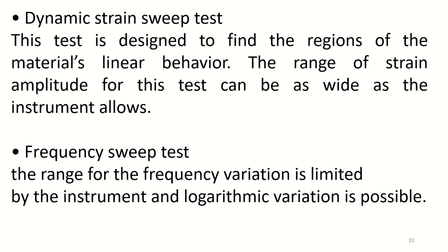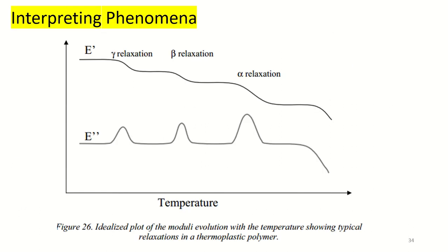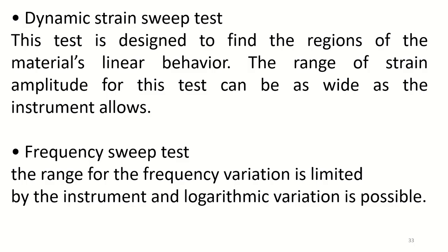Logarithmic variation is less time consuming, however. A good provisional value for the frequency has to be chosen. In general, 1 Hertz is recommended for the dynamic strain sweep test. The second one is the frequency sweep test.